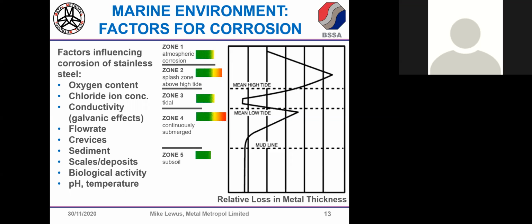So we get a peak in corrosion, or at least a peak in the aggressivity of the environment, where we've got high chloride, but in the splash zone we've also got erosive effects of the waves. Then there's a drop back because those things aren't as relevant, but then we find there's another peak just below the mean low tide level, and that's due to two things. One, microbial activity. An important aspect there is sulfate reducing bacteria. But there's also an impact of galvanic corrosion as a result of differential levels of oxygen. So we get an accelerated low water corrosion rate just below the mean low tide level. Then we drop off as we get to the mud line or the seabed because the level of oxygen goes down. If there's no oxygen, you're not going to get a corrosion process.